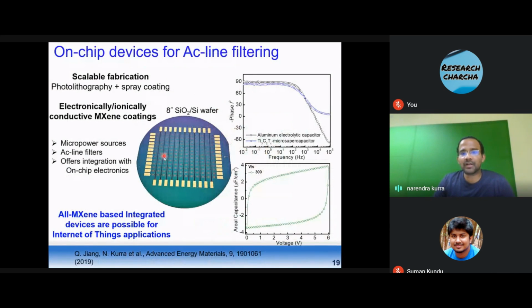And in our study, we have shown that using photolithography and spray coating on an 8-inch silicon wafer, we could make 100 devices of MXene micro supercapacitors. And when we check their phase angle versus frequency response, you can see the phase angle of 90 degrees is almost maintained until 120 hertz. That is a requirement for AC line filtering of a 120 hertz signal. And this can be operated at a very high scan rate, like 300 volts per second. In terms of capacitance at 120 hertz, it's around 30 farad per cubic centimeter, which gives rise to energy densities much higher than bulky electrolytic capacitors. So this is where MXene micro supercapacitors can fit and be compatibly integrated with electronic circuits for AC line filtering applications.